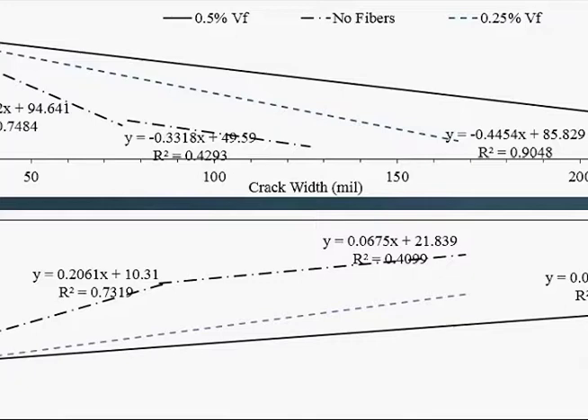One important thing here: in fiber concrete thin overlays, we do not provide dowel bars. Sometimes we do, but most of the time we don't. So when you talk about load transfer, it is very important to mention at what crack width you are testing. Why? Because in conventional concrete you have dowel bars, and the load transfer sensitivity with respect to crack width is not that much, but for this one it is. So when we talk about load transfer in fiber reinforced concrete, we should also look at what crack width we are talking about. If we are comparing two joints and the crack widths are different, then we are not comparing apples to apples.